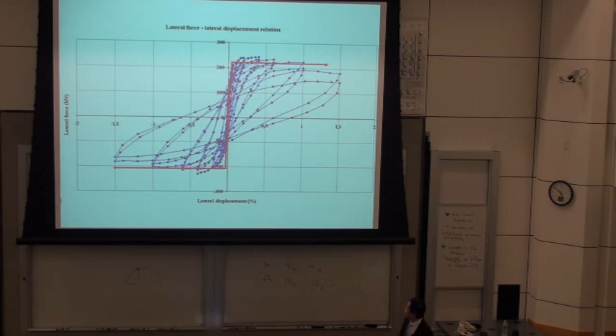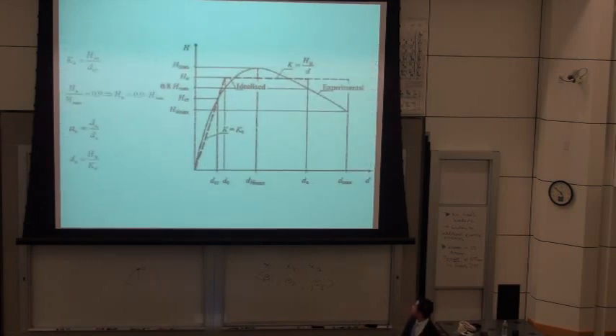You have the hysteresis with the closed circles. As I said, three circles each time. Then you go to the next step and try to fit an envelope, in this case very easy to do, a bilinear envelope. If you have the envelope, this is just copy-paste from the book from Tomasevic. He said you end the test when you reach 80% of Hmax. That means this is the so-called ultimate displacement.